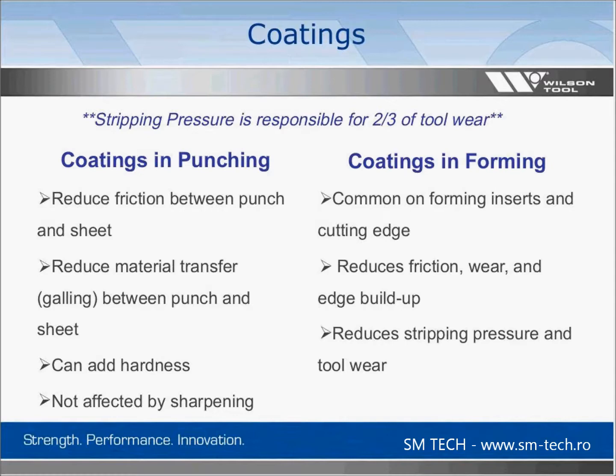Coatings are also used in forming. They're very common on forming inserts and on the cutting edge of the forming tool. They help to reduce friction, wear, and edge buildup. They greatly reduce stripping pressure and tool wear. Coatings are often used on the forming insert in high carbon materials to help reduce that stripping pressure and actually allow it to strip out of the sheet.